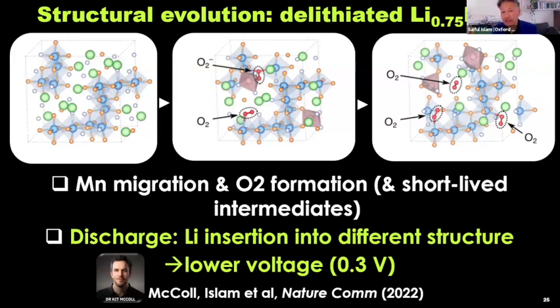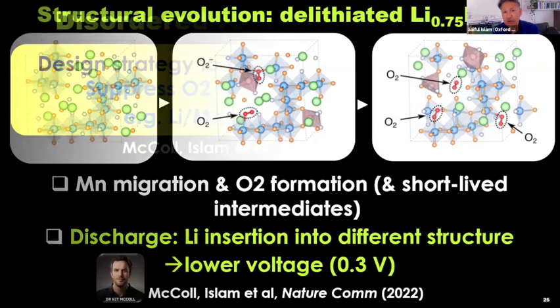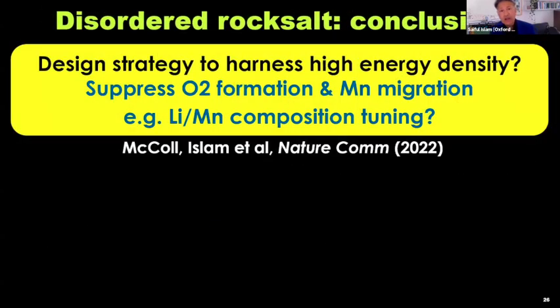And we published that a couple of years ago in Nature Comms. This is elegant work by a postdoc in my group, Dr. Kit McColl. So what are the implications? Well, now we understand what's going on, we can suggest a design strategy to harness high energy density rock salts. We want to suppress O2 formation and manganese migration. And we've been doing that by modifying the lithium manganese ratio by composition tuning. And as I said, that was published a couple of years ago.